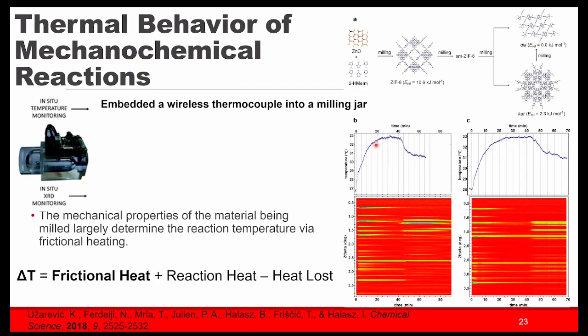You can see the increase in temperature here. And then as soon as this second phase nucleates here, the ZIF8, you really can see that the frictional properties of that phase are lower, and so the temperature itself drops. By looking at the thermodynamics and some of the energy calculations in this work, they were really able to show that it's this frictional heating term that really dominates for these types of reactions.